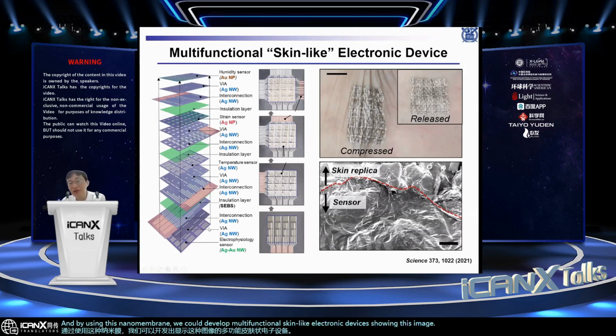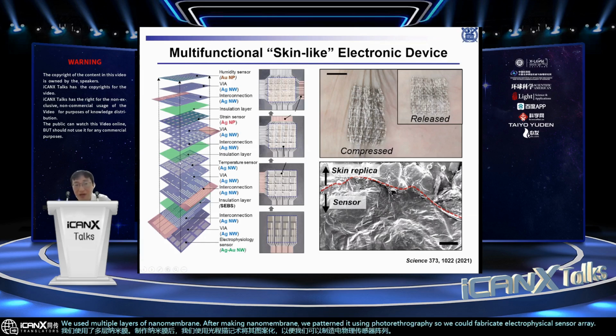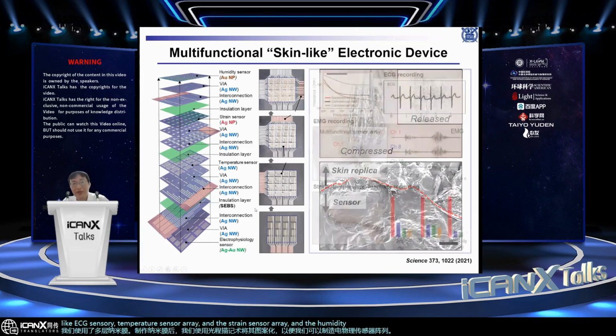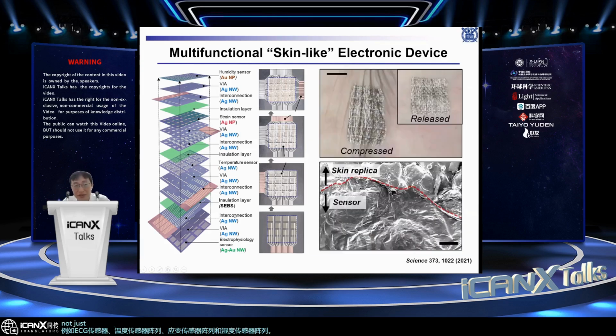We used multiple layers of nanomembrane. After making a nanomembrane, we patterned it using photolithography. So we could fabricate electrophysiological sensor array, like ECG sensor array, temperature sensor array, and the strain sensor array, and the humidity sensor array. Not just electrodes for the sensors, but also interconnection and the via structure could be made with the nanomembrane by using photolithography.